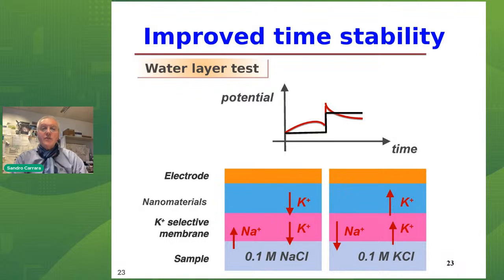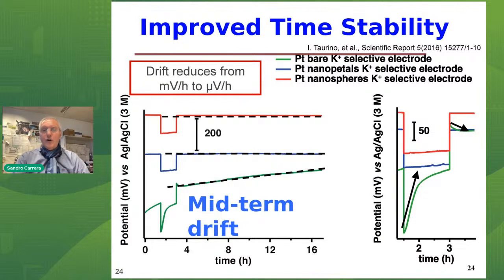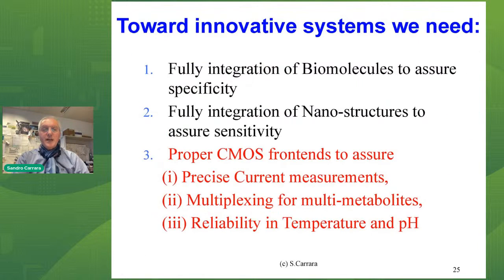I mentioned the fact that we have a non-stable open circuit potential in the case of a selective membrane for ions. Well, it has been demonstrated, and we have also published, that the potential becomes very stable if we nanostructure the working electrode, thanks, for example, to nano platinum or nano gold. And here you see the result. There was a huge drift if the electrode was not nanostructured. Instead, with both nanopetals and nanospheres, we have quite straightforward and very stable in time measurements of the open circuit potential, dealing with a certain concentration, for example, of potassium ions.